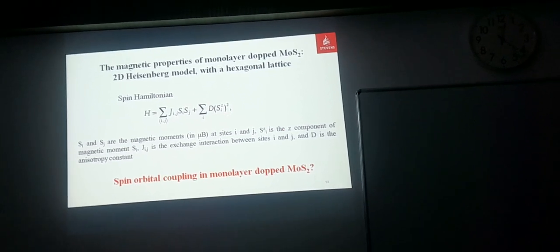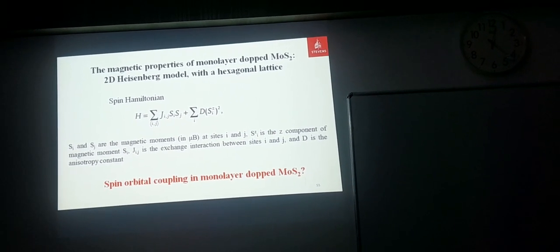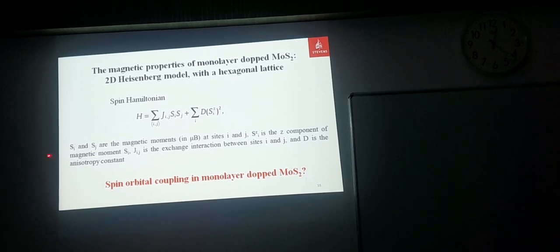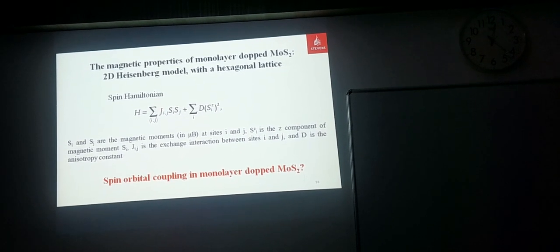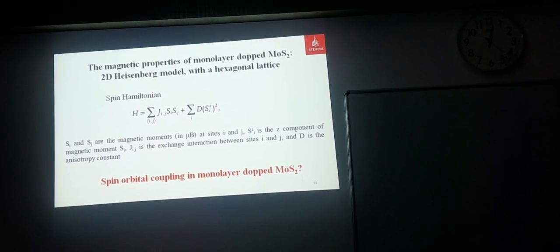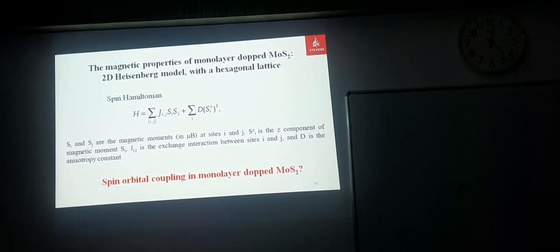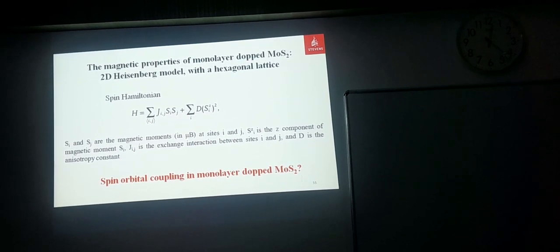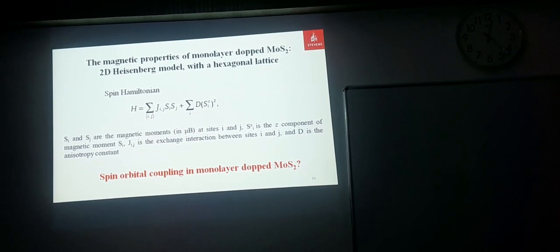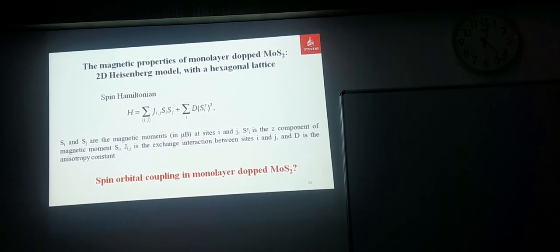So just forget all the other stuff. When we consider this Hamiltonian, this Jij is basically the spin-phonon coupling strength. We are trying to understand the value of this spin-phonon coupling in terms of the theoretical part and the experimental part that we observe in our system. What we realize here is that the spin-phonon coupling is directional dependent, for the in-plane and out-of-plane vibrations in this system. That's why you see two different slopes in these two different cases. This is not published yet, so very soon we are going to submit this paper.